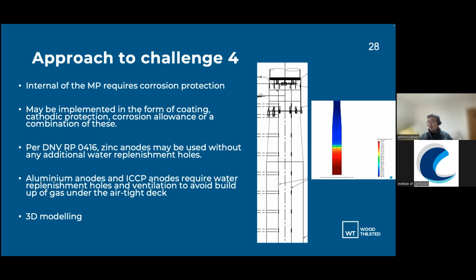Whereas if we use aluminium anodes and ICCP anodes, we do require water replenishment holes as well as ventilation to avoid buildup of gas, as well as to buffer the pH inside. For internal of the monopile, the other approach that we have to consider is the 3D modeling, to ensure that we do have protection all the way throughout. Getting electrical continuity can be a bit more difficult to do, but it is something that we have done, and it can be employed.